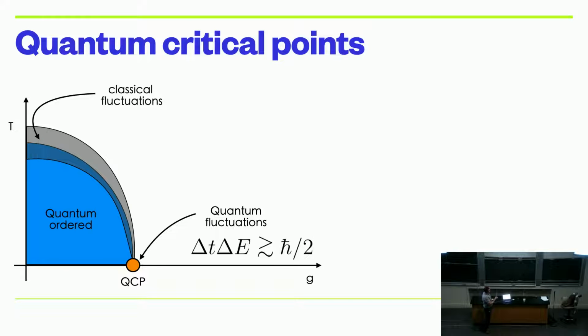So far, we've talked about transitions in electrons that happen at finite temperature. So I'm cooling the system down, and it becomes antiferromagnetic, or becomes ferromagnetic, or whatever, and that's the transition. But let's say I've got another tuning parameter. Let's say I can change the system non-thermally. I don't just have to change temperature, I could change the magnetic field, or the doping, or the sulfur content, or whatever my parameter might be. And let me call that G. And for whatever reason, the transition temperature of this system starts to go down to zero temperature.